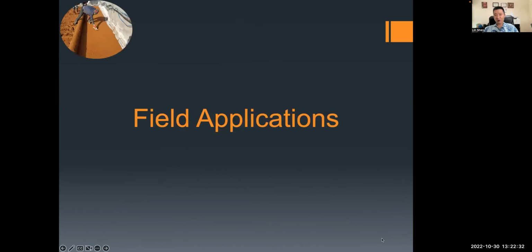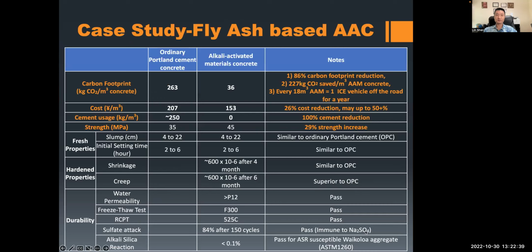And lastly, let us focus on field applications in both Hawaii and China. This table shows a case study of fly ash-based AAC. It shows us the carbon footprint of alkali-activated concrete. Here, the second column shows ordinary Portland cement concrete. We can see more than 85% reduction in carbon footprint. Cost-wise, in this case, we have 25% cost reduction. In some cases, it may go up to more than 50% reduction in cost.